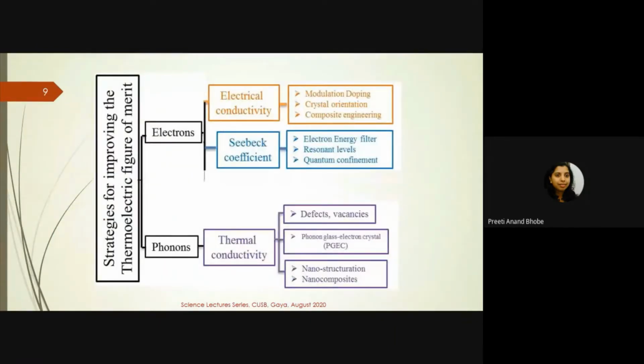It is also known that to improve the figure of merit, you have to focus on your electron concentration as well as the phonon concentration, because phonons are your lattice vibrations. It is the thermal conductivity term that comes in the denominator. So from a solid state point of view, which factors control our electrical conductivity, Seebeck coefficient and thermal conductivity? Electrical conductivity can be modulated by having different crystal orientation, making different compositions, and things like that. The Seebeck coefficient will also get affected if you play with the carrier concentration and the band levels in the material. Thermal conductivity, on the other hand, is very sensitive to defects and vacancies. If you make nanostructures, then also one can see an effect on thermal conductivity.